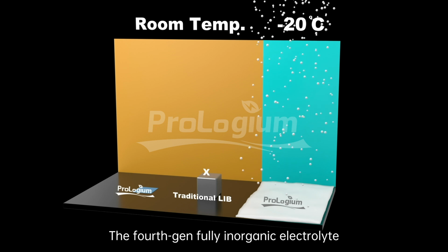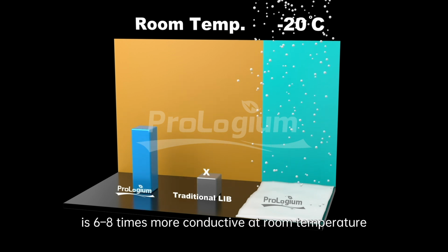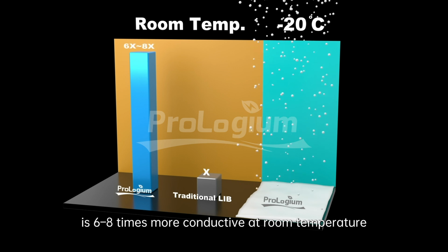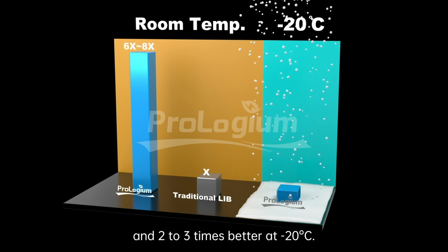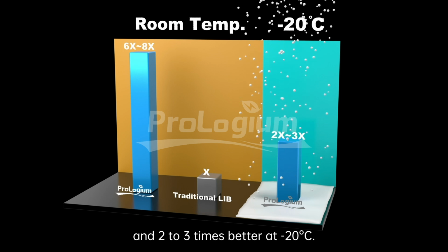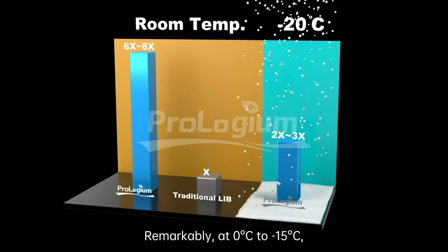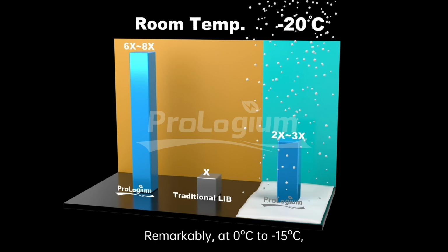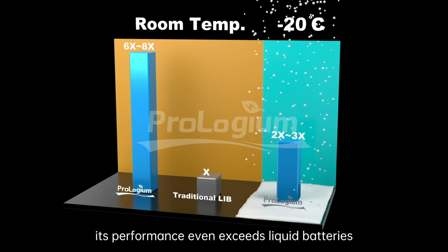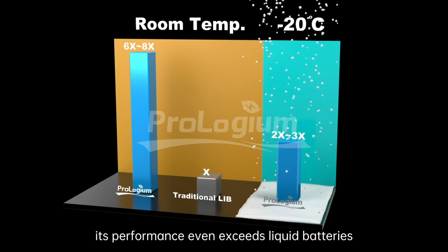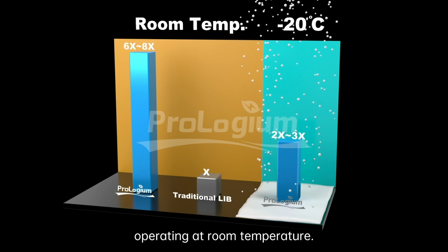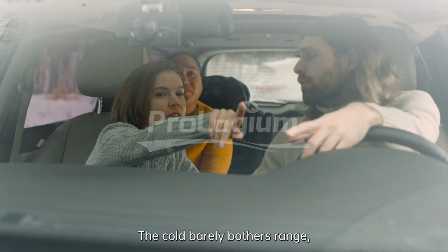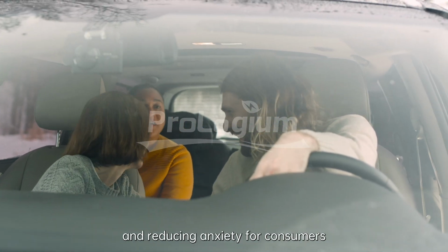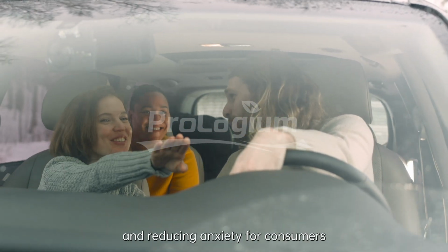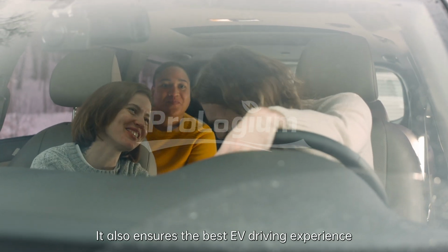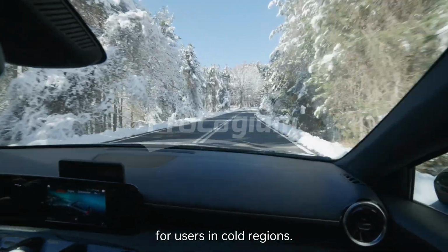The fourth generation fully inorganic electrolyte is 6 to 8 times more conductive at room temperature and 2 to 3 times better at minus 20 degrees Celsius. Remarkably, at 0 degrees Celsius to minus 15 degrees Celsius, its performance even exceeds liquid batteries operating at room temperature. The cold barely bothers range, making predictions reliable and reducing anxiety for consumers. It also ensures the best EV driving experience for users in cold regions.